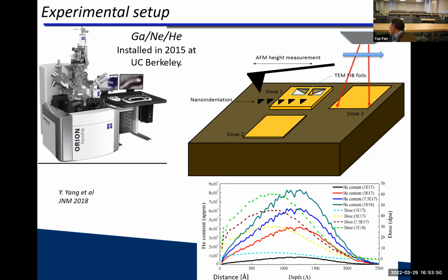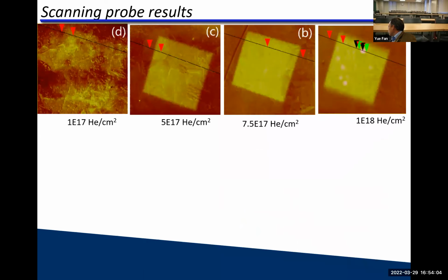But we usually do between 1 × 10^17 to 1 × 10^18 helium ions per square centimeter. So pretty hefty dose. That leads you to about 40 or 50 dpa of displacement damage. So let's see what that looks like. So here's 1 × 10^17 helium ions, 5, 7, 1 × 10^18 in copper. And we see, of course, with the AFM, the rising of the surface. And at high dose, like in this instance, we see these features popping up, which are actually blisters. We're going to see in a second.